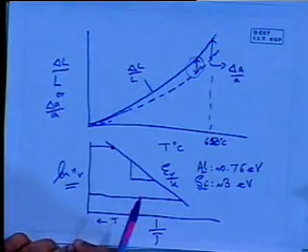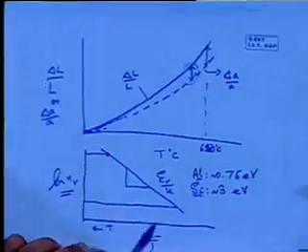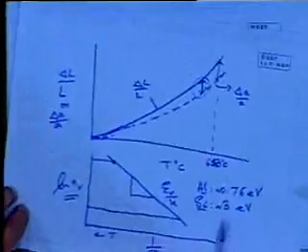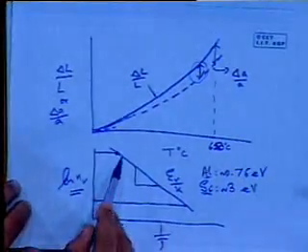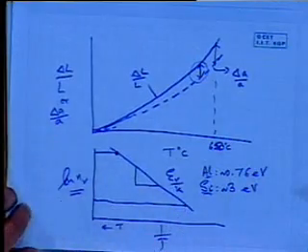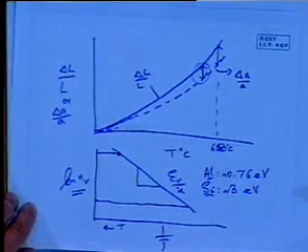And then I bring it back to room temperature and I measure how many vacancies. Much more vacancies than what I would expect by equilibrium cooling. This slow cooling got me here, because those vacancies had time to get out of the system. So by quenching, I can artificially create structures that are not equilibrium and play with the properties. We won't go into that, but just to point that out in passing.